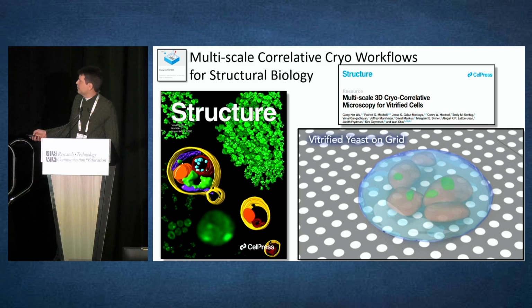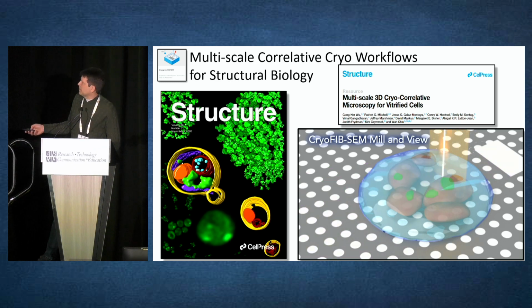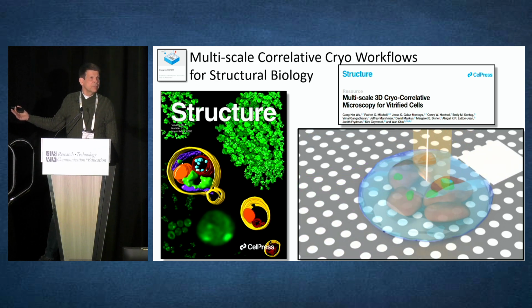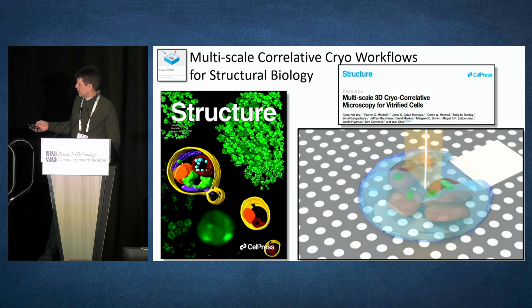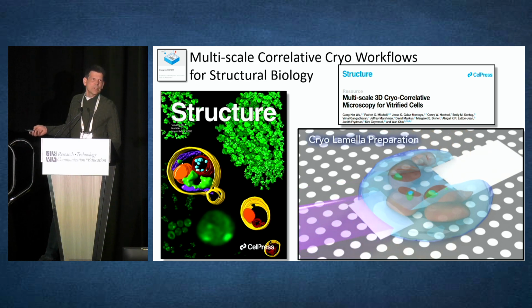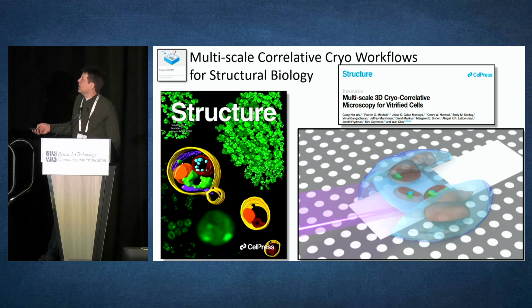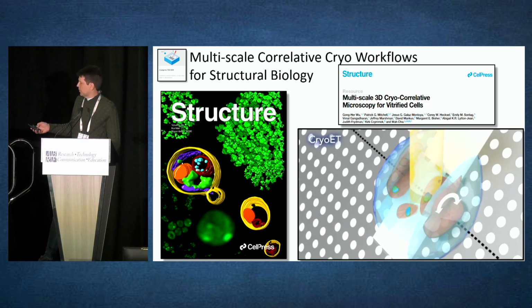And I think if I push the button, you can actually see there's your frozen cells vitrified on a surface. The ion beam comes in and mills. You image the surface. You keep watching because you can see contrast, right? So you can see where you're going. You can get to your target, which may be a fluorescent protein. And then once you get your target area, then you come in and mill it from the other side so you can make your lamella. And then finally, you can take the sample and do your cryo-ET.